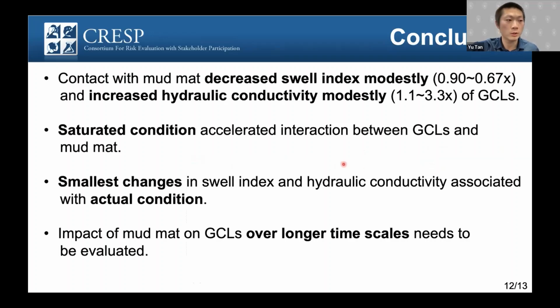So these are the conclusions. First, the contact with mud mat does have some effect on GCL. It affects the swell index, decreasing the swell index and increasing the hydraulic conductivity of GCL. And the saturated condition accelerates the interaction between GCL and mud mat. The smallest change happens under actual conditions, so it's favorable that our disposal facilities should work pretty well. But for a longer time scale, we still need to evaluate, because our method of mixing the concrete and the water to create the solution to represent the pure water in concrete is still not quite accurate.